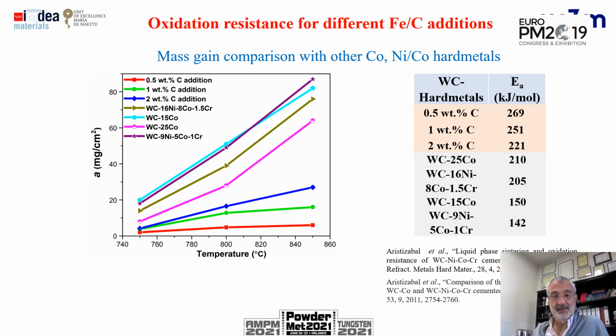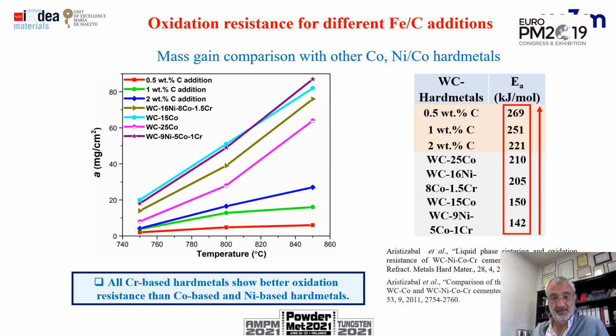And also we have tested the mass gain in terms of oxidation, and we have compared our material, which is those on the bottom part of the graph. The red one is the material with 0.5% of carbon and 3% of iron. And here in this pink color and this green color we have some conventional cemented carbides, and we have seen that the mass gain growth in comparison with our materials is much higher in the other conventional cemented carbides. So that means that we are getting a good combination of oxidation and wear for this material. So this is just a comparison in between all of them.